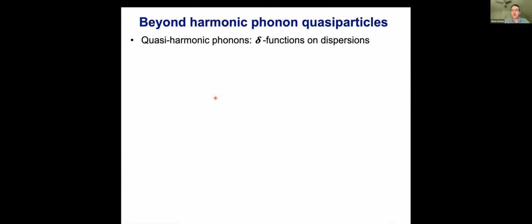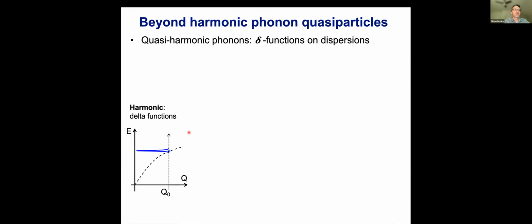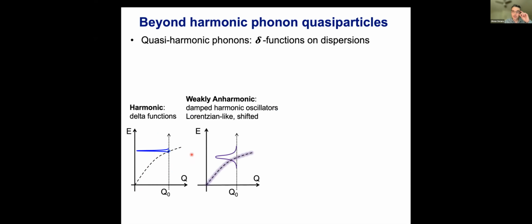So the underlying perspective we have when we do these x-ray studies and generally phonon spectroscopy is to try to understand effects that go beyond the standard phonon quasi-particle picture. We all know that if we have a harmonic system, we have well-defined excitations in terms of lattice vibrations. So collective modes that define quasi-particles are long-lived, and those are distributed on underlying dispersions. We can compute this from DFT nowadays. That's become pretty routine. However, there are strong anharmonic effects, or important anharmonic effects, that often develop in real materials as you increase temperature, for example. You can hope to understand this in the framework of the damped harmonic oscillator. You can extract phonon lifetimes. I think Michael Manley will focus on this topic in the next talk, and that connects with thermal transport. I'll show a little bit on the thermoelectrics.